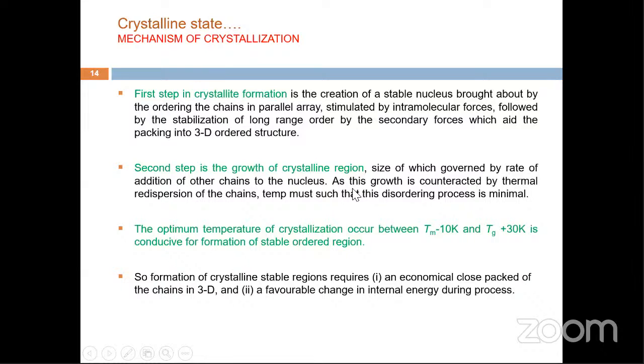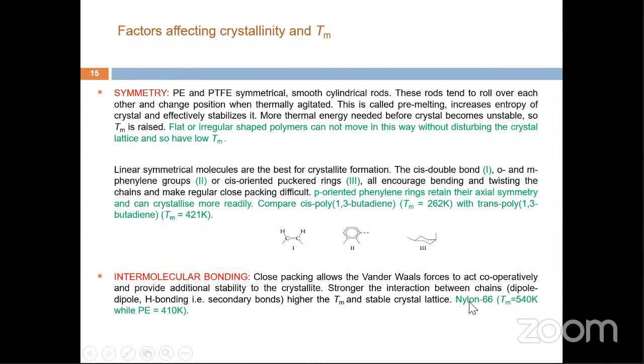So there the temperature has its role. Generally the optimum temperature for crystallization is between 10 degrees centigrade less than the melting point and 30 degrees centigrade higher than the glass temperature. So we have narrowed down the temperature range where we see crystallization occurring. For formation of a crystalline stable region, we require economical close packing of chains in 3 dimensions and a favorable change in internal energy during the process.